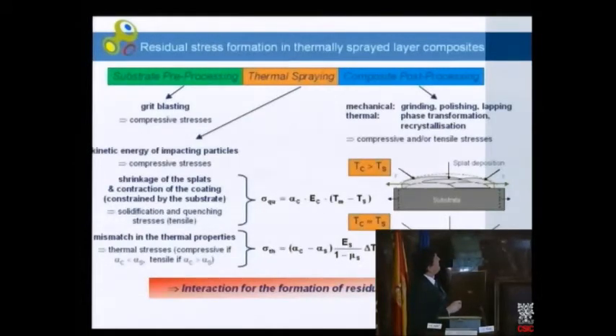The mismatch in the thermophysical properties is well known, but we again have to face that there are also a lot of process-induced influences. For example, the well-established grit blasting or laser structuring and machining or water jet machining in the pre-processing. And this mainly causes compressive stresses. The thermal spray process itself will influence, again, a variety of stresses. There are tensile ones, there are compressive ones with respect to time.